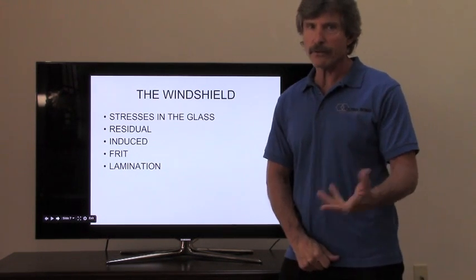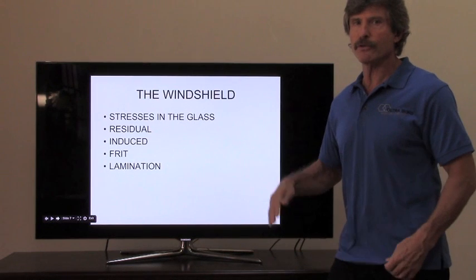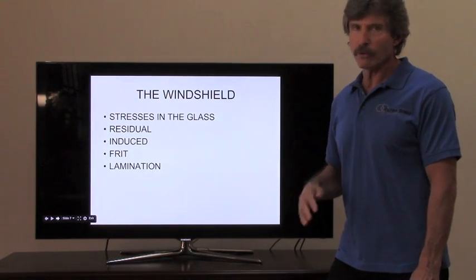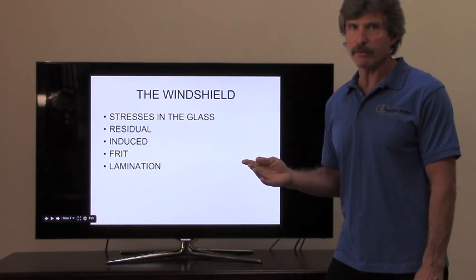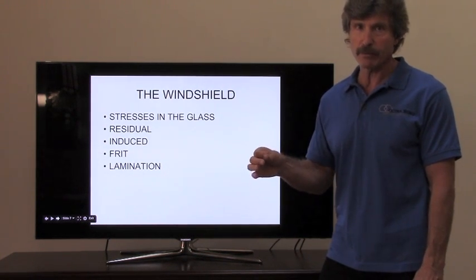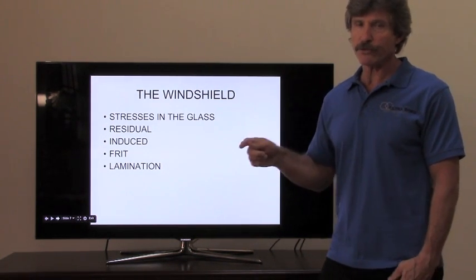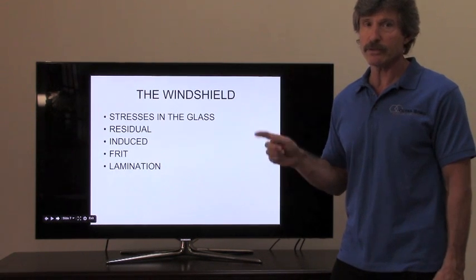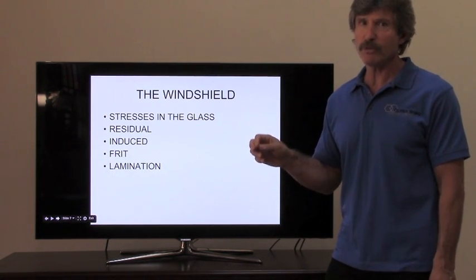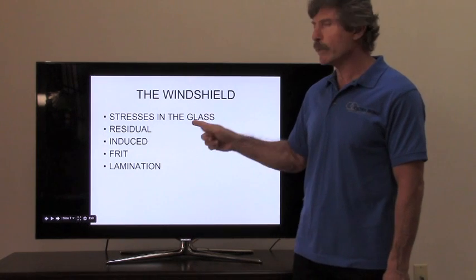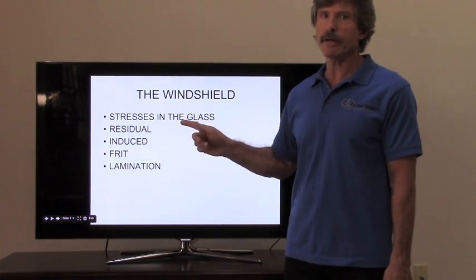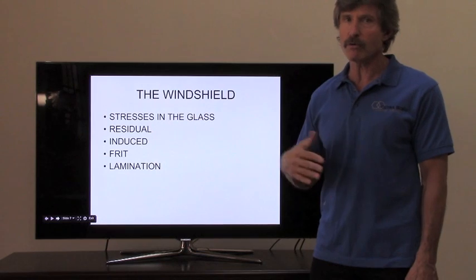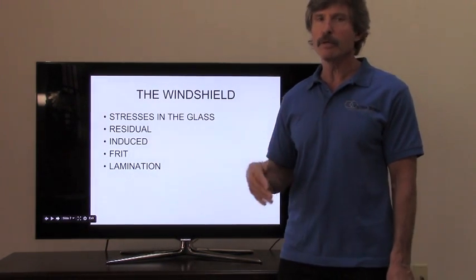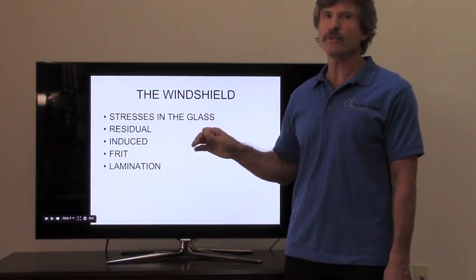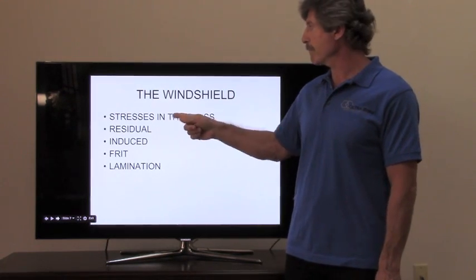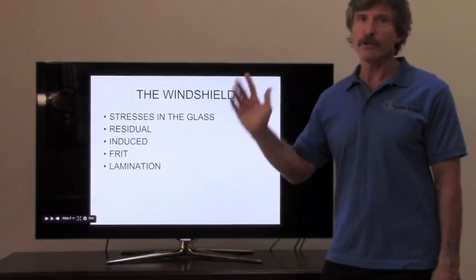If you fix cracks, so you're going to start fixing cracks, what you're going to notice on your edge cracks is over half of them, the impact point is going to be about the size of a grain of sand, a pinhead size. That's all it takes to cause an edge crack, is a surface chip. A surface chip the size of a pinhead in the weak spot will cause an edge crack. It does not even have to be a star or a bullseye or a combination break or a partial bullseye. All you need is a surface chip in the weak spot, which is on the frit area, and you will have an edge crack.